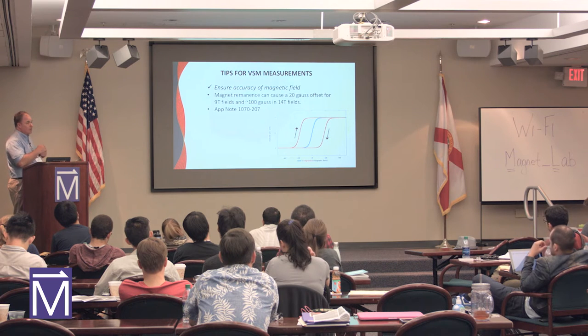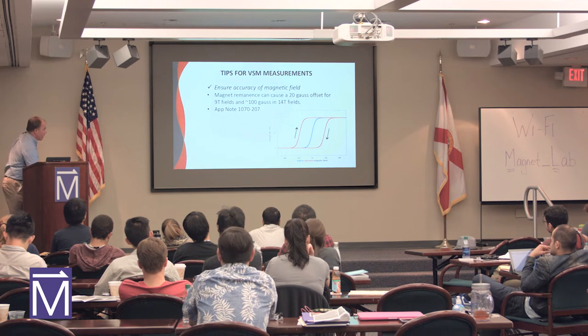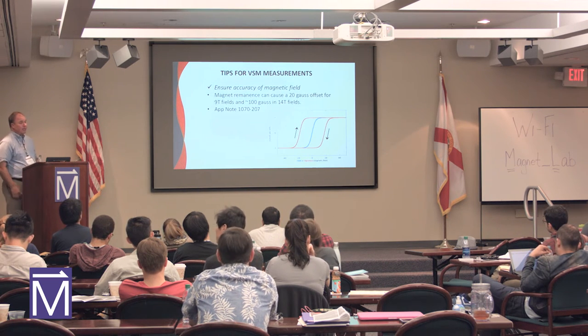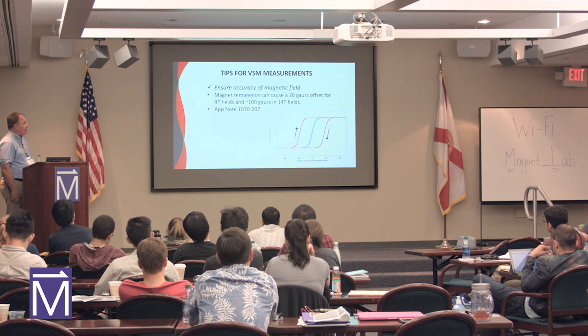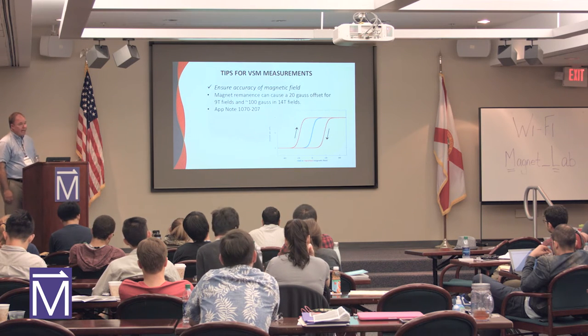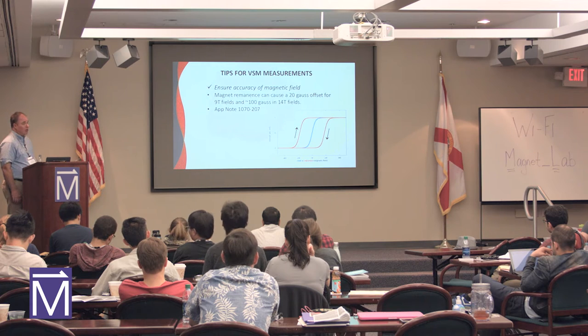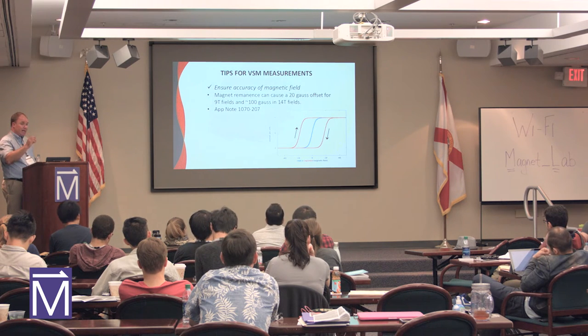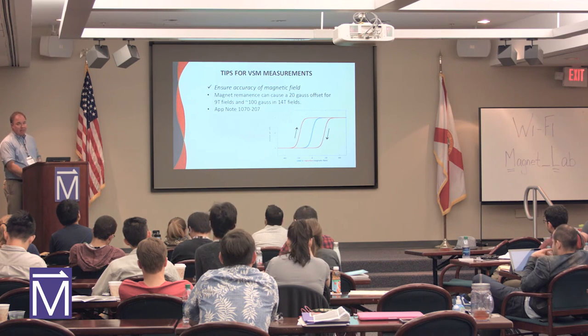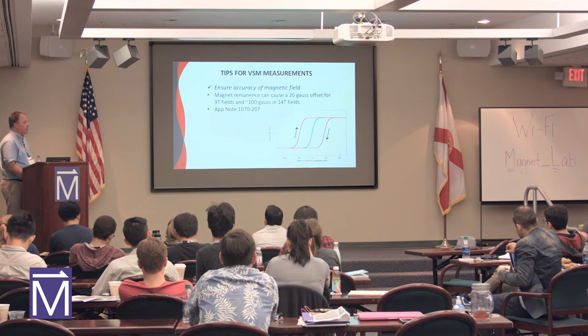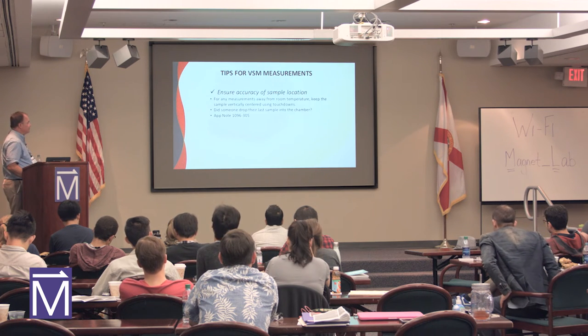Remnant field. Superconducting magnets have a remnant field. There are a couple of tricks that you can do to minimize the remnant field. It's about 20 Gauss in the 9 Tesla system and 100 Gauss in the 14 Tesla system. So essentially, if you're making measurements at low magnetic fields, you have to worry about the remnant field, because that may dominate your experiment. And we have a nice app note on that.